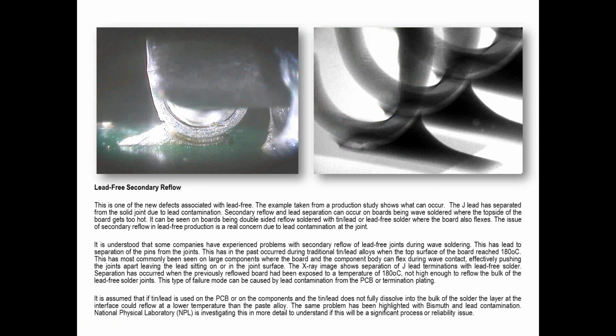So if you've got a lead-free joint on the top side of a printed circuit board and it has some lead in it, and you have a higher preheat, which you typically do with selective and wave on a lead-free process, potentially the top joints can reflow. And if you look at it in a little more detail, when you separated the pins away, you might see an image like I show you on the right-hand side. And this is the bottom, or the cup, of the solder joint where this J-lead termination has been literally separated from.